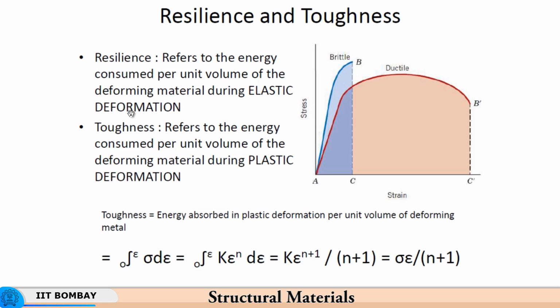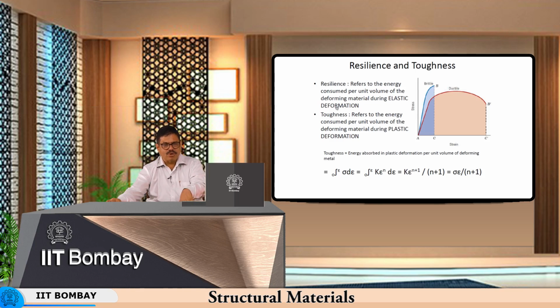So, if you have this way you can calculate the amount of volume that is needed to store certain amount of elastic energy. So, per unit volume you can store so much of energy in a given material. So, if you have a spring which is expected to store certain amount of elastic energy, you calculate the volume of the material needed to store that much energy. Similar is the case for plastic deformation, for forging for example. You want to forge a railway axle or a wheel of a railway train. So, you know how much is the energy that is needed for deforming 1 unit volume of material. You know the volume of the material needed for forging of an axle or the wheel of a railway train. Then you know how much of energy would be required for forging, that total energy required for actual forging of the axle or the wheel of the train.